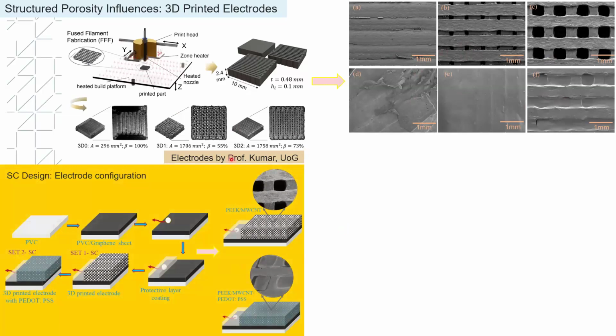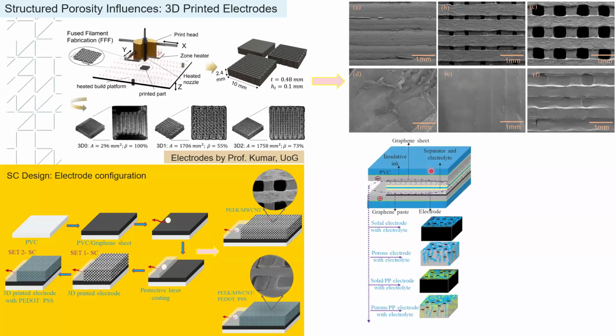For example, you can see from here that we took a PVC substrate and attached the PVC with a current collector, a graphene sheet, and then on one side we use the electrode, and then we attach the 3D electrode here. So you can see that the 3D printed electrode we attached on a step, and then we bonded this one with a conductive polymer. Then you can see here that depending on the type of electrode we used, for example, when we have a bulk sample, there is no porosity.